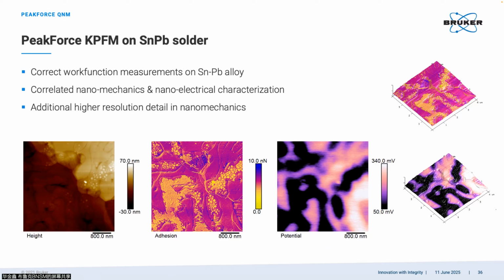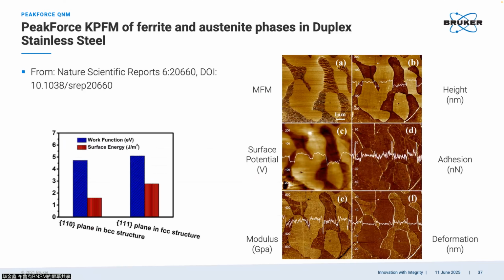The KPFM is used to study the potential distribution on the surface. And from the potential distribution, we can capture the work function of our materials. So we can combine the mechanical mapping and the potential mapping. We can clearly say those soft parts, those large adhesive parts, have a lower potential. The lower potential means there are more electrons on the surface, so it should have the lower work function. So as such, we can know this part is our lead. Combining the mechanical mapping with other techniques expands the application of our nanomechanics.